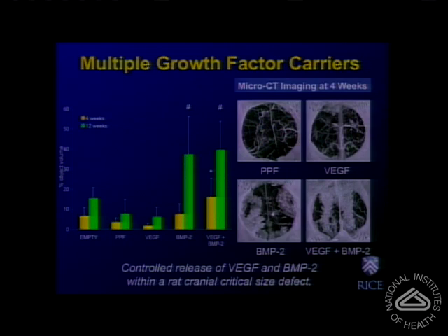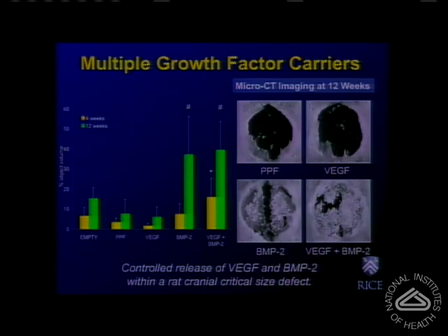We see a lot of bone formation when we deliver bone morphogenetic protein 2 or the combination of vascular endothelial growth factor and BMP2 at 4 weeks. Here we have the results of the quantitative analysis of bone formation. At 4 weeks, we have a beneficial effect of the dual delivery of the two growth factors. However, at 12 weeks, we don't see any difference between dual delivery and single delivery of bone morphogenetic protein 2.